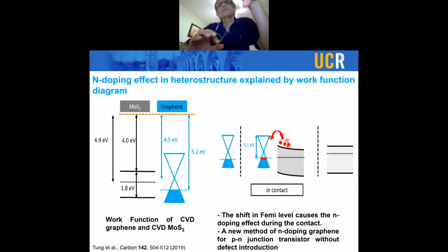I would not go into the details of this, just to tell you that we did measure the work functions of all the materials. That means pristine graphene, pristine MoS2, and the heterostructure. Based on this, the left-hand side shows the work function and the Fermi levels for the MoS2 and graphene, and the right side shows the heterostructure, which shows that there is an electron donation from the MoS2 to the graphene, thereby n-doping the graphene through the process of heterostructure formation.